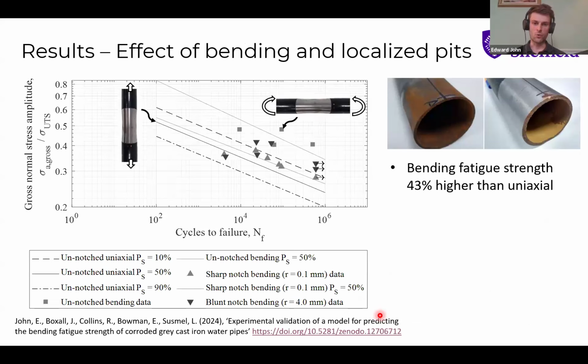So looking now more at the strength side of things, the durability of these pipes. So this shows an SN plot. This is basically recording the number of cycles to failure for each of the tests we did. So along the bottom, cycles to failure, and that's cycles to the start of water loss. And then up the side, we have a normalized stress amplitude. So that's basically the stress experienced by the pipe as a proportion of its static strength.